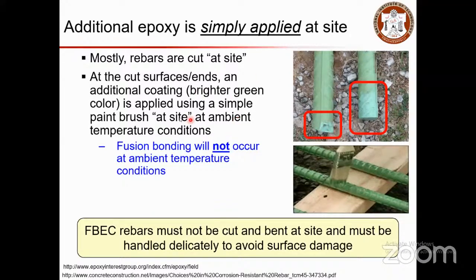So the cut surface is coated using a simple paintbrush at ambient temperature conditions. Fusion bonding will not occur at ambient temperature conditions, so these things are not going to serve the purpose. So the advice is that the FBEC rebars must not be cut and bent at the site and must be handled delicately to avoid surface damages.